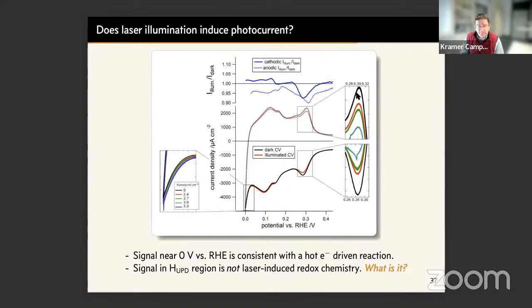If you move now out towards this UPD region, you see something perhaps a bit more curious, right? So the first thing is shown up above, and that is that there is a laser-induced current only where there is existing current features, right? So it's very small if you move out here into the double layer. And if you look at these UPD features, what you see is that increasing laser fluence, so once again, the black is 0, increasing laser fluence results in a decrease in current going in both scan directions.